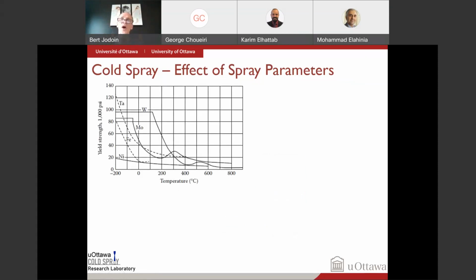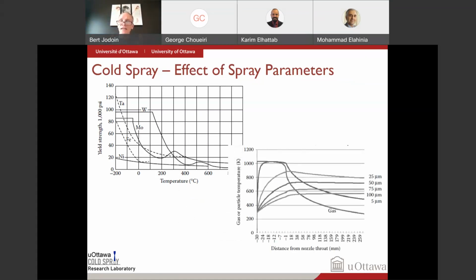Temperature is important. The particle temperature is important because you know, right, the yield strength as a function of temperature, you know that the yield strength can drop quite drastically as a function of temperature. So if we want to spray materials, we'd like to get the particles as warm as possible just before the impact, but it's kind of difficult because in the cold spray process, the temperature in the gun drops very drastically. So it's a bit hard to achieve, but nevertheless, here it tells us a different story, right?